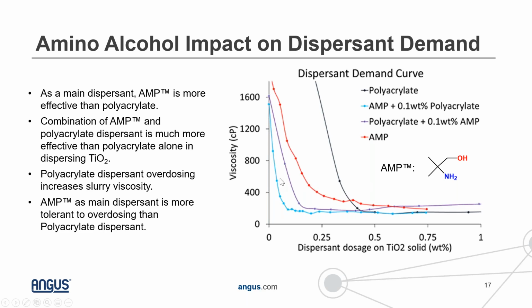And so really, the best case scenario that we found is the case of this light blue line, where we pre-added 0.1 weight percent of the polyacrylate dispersant and then titrated in AMP. And so we get a very low viscosity and a very low dosage of AMP in the polyacrylate dispersant. So really the ideal scenario to get a really high quality dispersion for this grind was found to use 0.1% of the polyacrylate dispersant with around 0.1% of AMP, which minimizes the viscosity of that grind, which means that you're getting a very good particle size distribution in it.